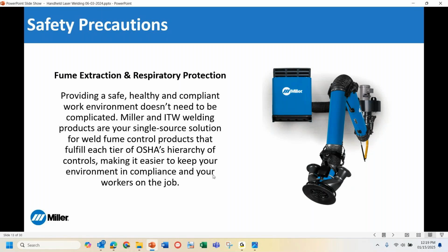What the studies that we have performed have found is that the welding particulate from laser welding is of similar size and characteristic to that which is produced with other more conventional welding processes like MIG, TIG, or stick welding. And so typically if you have fume capture devices in your facility for conventional welding, that is going to be considered acceptable for use with a laser welding process. But as always, it's best to have an industrial hygienist come in and find out if your fume extraction is sufficient for your operation.